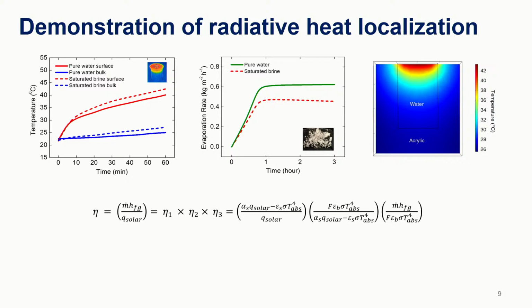So we can look at a conversion efficiency for this full process. So how much of the solar energy that's coming in is being used to evaporate the water. And we can break down that efficiency into three subparts. So the first one is the efficiency of our absorber. So this is the material that's really taking in the sunlight and converting that into heat. And so here we have a fairly high efficiency because of the optical properties of the selective solar absorber.